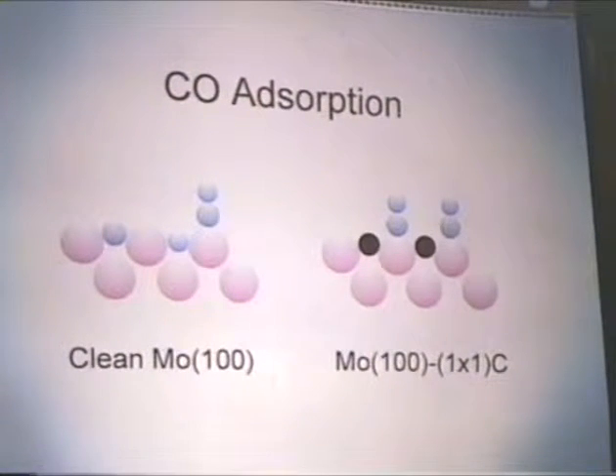And what Madix and co-workers, among others, found was that they would only begin populating this molecularly adsorbed CO once all of these sites have been filled with dissociated CO. Now, these correspond to four-fold hollow sites, and so only once they had saturated the four-fold hollow sites with dissociated CO did they begin to see the population of this molecularly adsorbed CO.